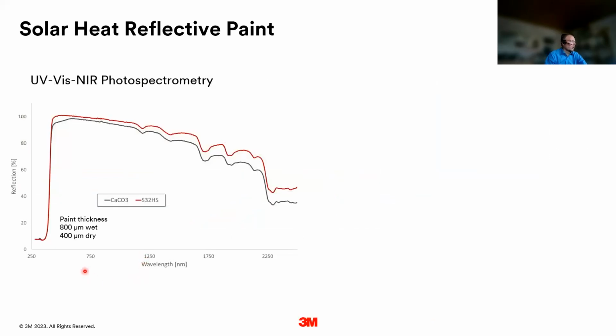So first of all, we had a look at the paints in a photospectrometer. So we measured these spectra, and here for the ease of reading and understanding this slide, I just plotted two lines. One is the reference with the calcium carbonate, and the other one, the red one, that's the paint with our bubble grade S32HS. And you can see that the reflection value is higher basically over the whole range here in the visible, but mainly in the near infrared range. We have a higher reflectivity compared to the reference paint formulation.